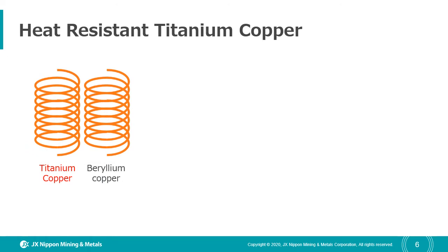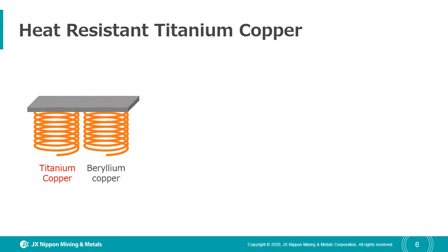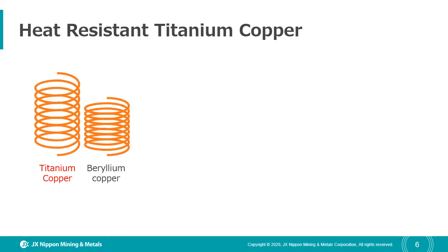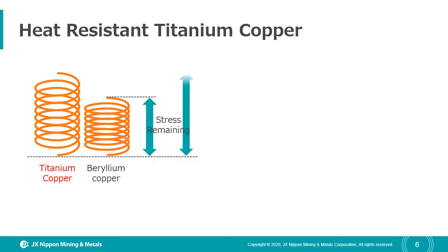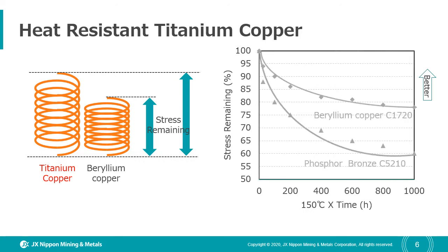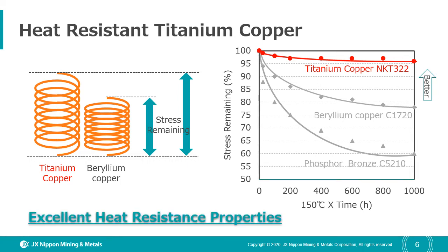Here are two springs made of titanium copper and beryllium copper. If we apply a certain load and make them shrink, and then heat them up and allow some time, once the load is removed, the springs lose their springiness. This parameter is referred to as stress remaining. This graph shows the stress remaining after heating to 150 degrees Celsius. Titanium copper shows excellent heat resistance properties compared to other copper alloys.